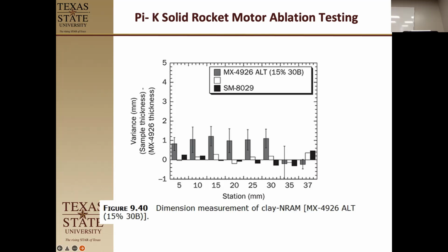This is the normal. This is with the one with the clay in it. You see more expansion in all of these. We actually start to see wear on the other two. Right here, the white one is again the normal one. And then by the time we get here, all of them are burning, or losing mass at that nozzle. So they're all losing mass. But the montmorillonite clay performed pretty close to the standard material. But notice the montmorillonite clay system foamed higher and probably insulated more.